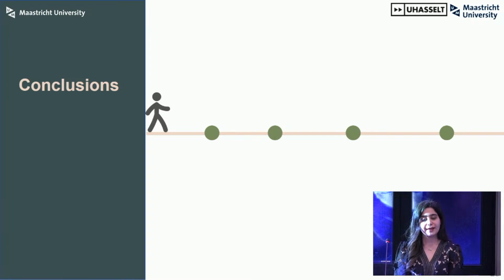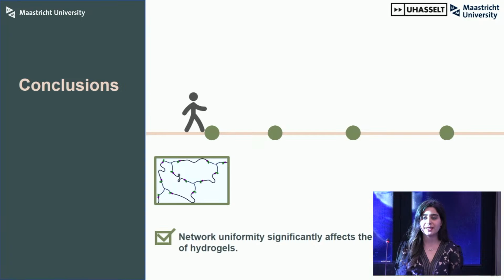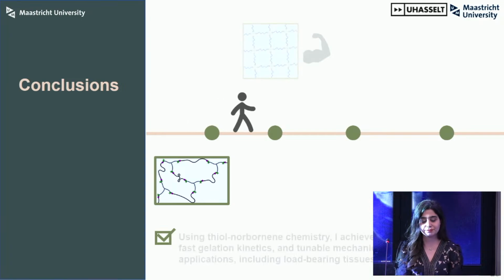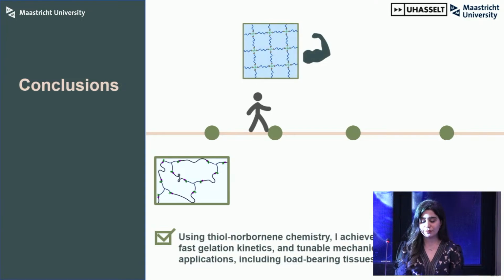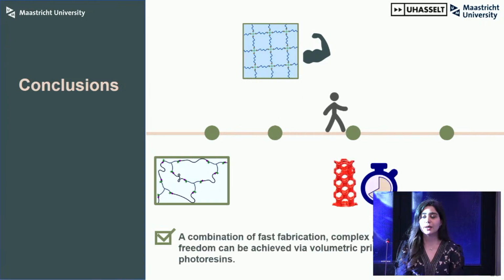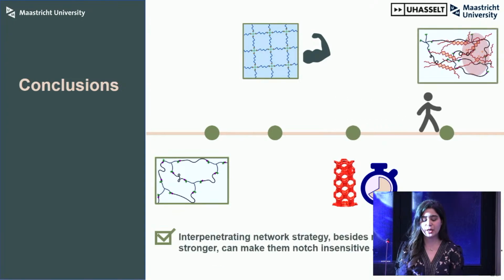As I conclude, I would like to highlight the key contributions of this thesis. I demonstrated that network uniformity significantly affects the mechanical properties of hydrogels. Using thiol-norbornene chemistry, I achieved uniform networks with fast gelation kinetics and tunable mechanics, suitable for various applications, including load-bearing tissues. A combination of fast fabrication, complex geometry, and design freedom can be achieved via volumetric printing and thiol-norbornene photoresins, which can be very beneficial for the biofabrication community. And lastly, the interpenetrating network strategy, besides making these hydrogels stronger, can make them notch insensitive and delay crack propagation.